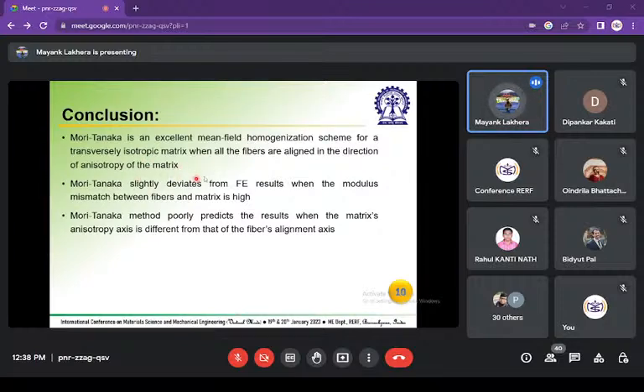But it is not a good method when the modulus mismatch between the fiber and the matrix is high, and also it poorly predicts the results when the matrix anisotropic axis differs from that of the fibers alignment axis. So fibers are aligned in the x direction. That means the semi-major axis of the fibers is in the x direction. But if we change the semi-major axis of the fibers to the y direction, then the Mori-Tanaka method does not predict the results to that accuracy. So that is all from our study. If you have any question, you can ask.